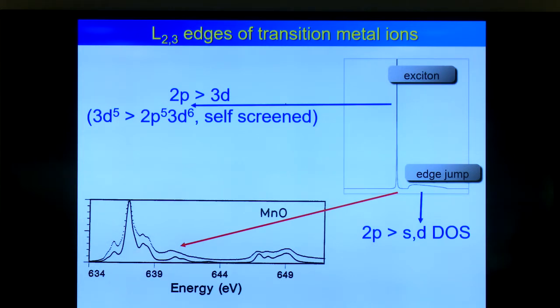Sorry, you mean saturated experimentally, not in the actual emission process? Yeah, the actual emission process. Oh, yeah. Because the penetration depth of the X-ray at the peak position here is only 10 nanometers. So it's a dynamical effect inside the material. Yeah. So it's the electron yield which saturates. Normally only fluorescence yield saturates, but in manganese oxide also the electron yield saturates.